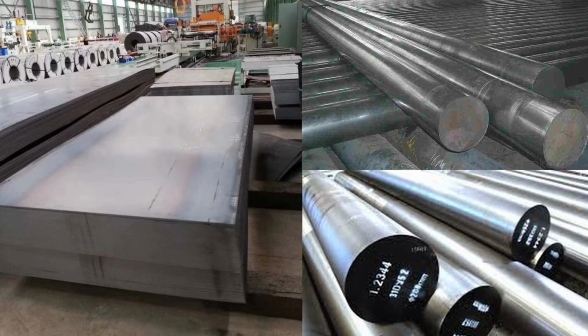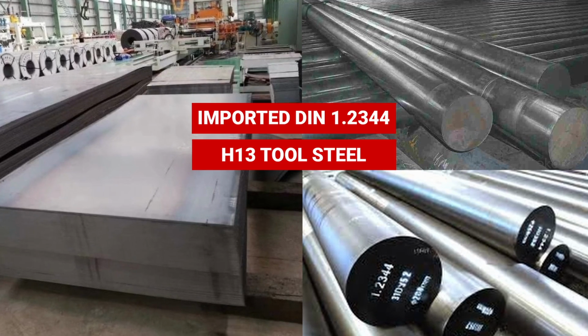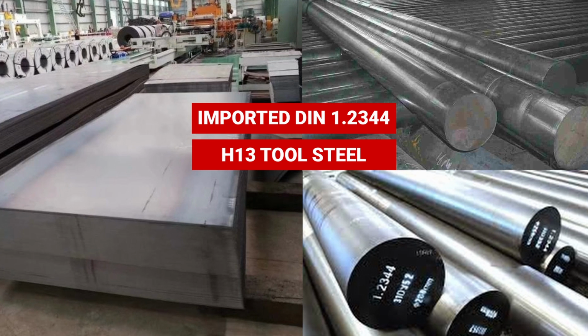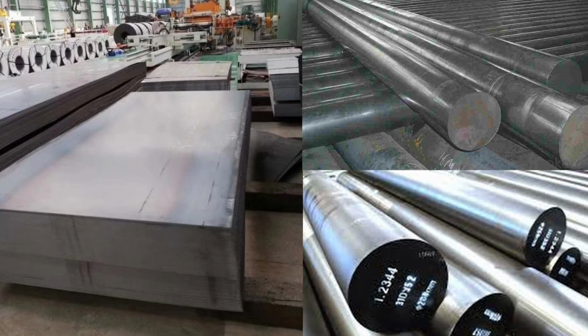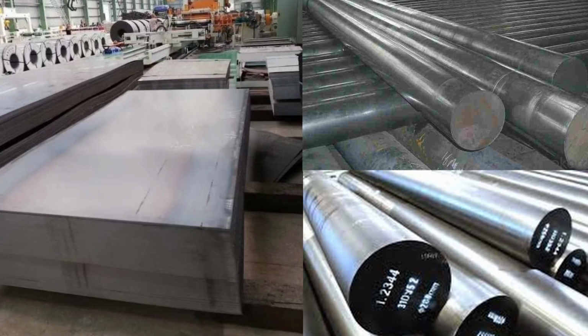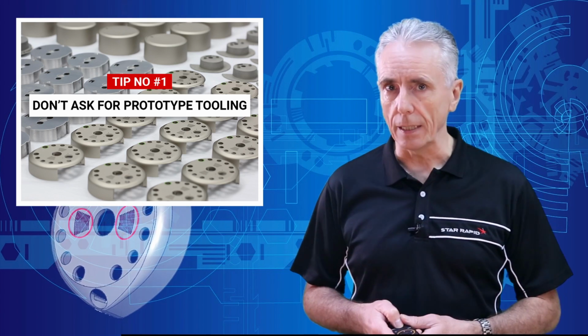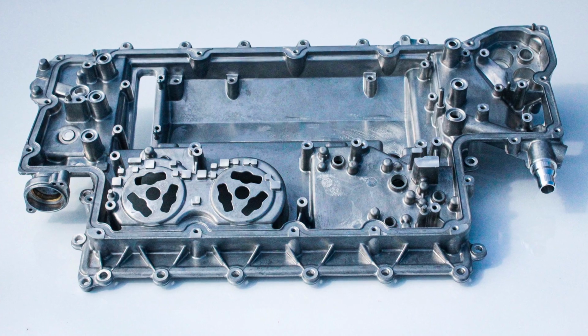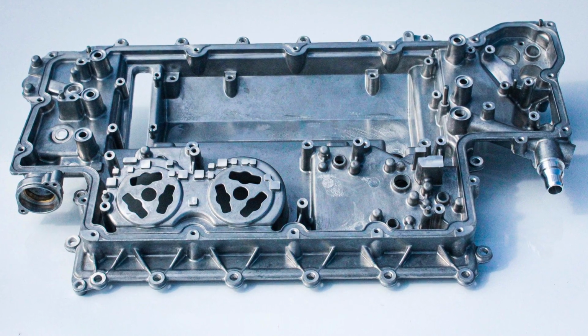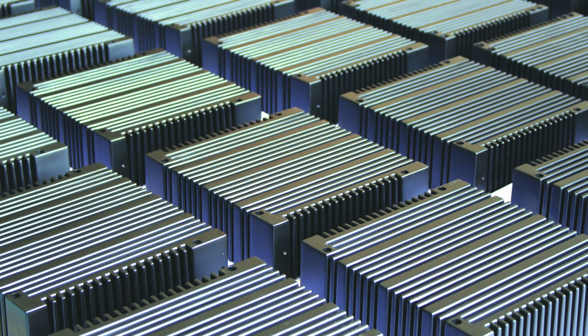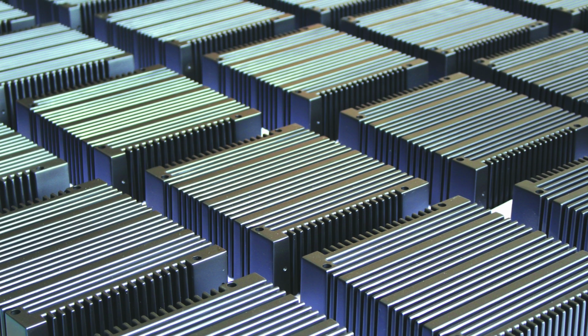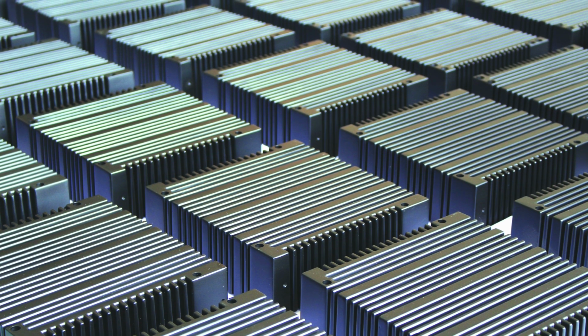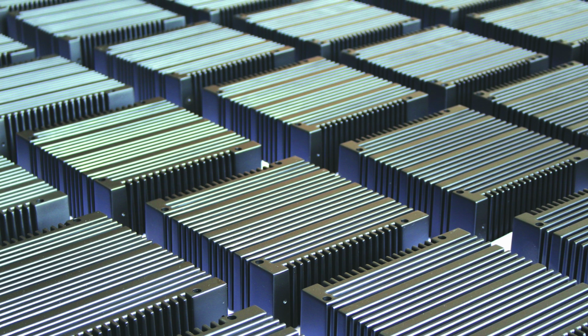So we typically only offer imported DIN 1.2344, aka H13 tool steel, hardened to between 43 and 47 Rockwell. They are in effect production dies. If you have a good quality steel and a great part design, coming to that bit shortly, you'll be able to get around 100,000 cycles out of a PDC die, and more if you use PVD coating on the surface.